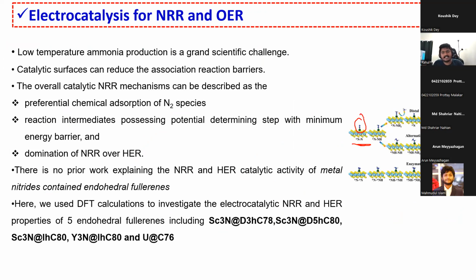First, as the name indicates, it's nitrogen reduction, so we have to adsorb the nitrogen to the substrate. The catalyst you choose should preferentially adsorb nitrogen. Then it has to convert this nitrogen to ammonia. For the conversion, N2 will convert to NNH with the addition of a proton. Then NNH will convert to N2H2 with again the addition of a proton. Then this will convert to N, an N radical. Then again we add a proton, then it will go to NH, then NH2, NH3. This is the pathway for the nitrogen reduction reaction.